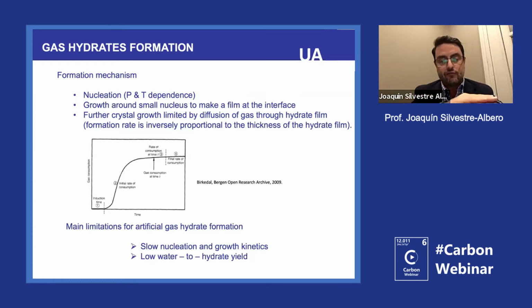In the moment that you make a first layer of gas hydrate at the interface between the gas and the liquid, the further growth of this gas hydrate is really difficult because you need the methane molecule to diffuse through the crystal to reach the other side. And then what happens is that the formation rate is inversely proportional to the thickness of the hydrate. So at the end, the message is that once you get a layer, the system is stopped. And that makes the production of bulk gas hydrates really difficult, because it's a very complex system due to the limited gas-liquid interface.